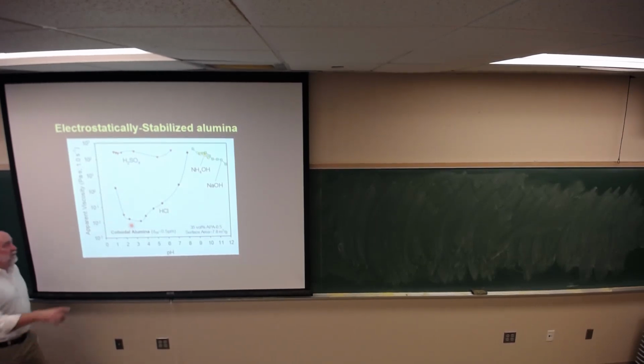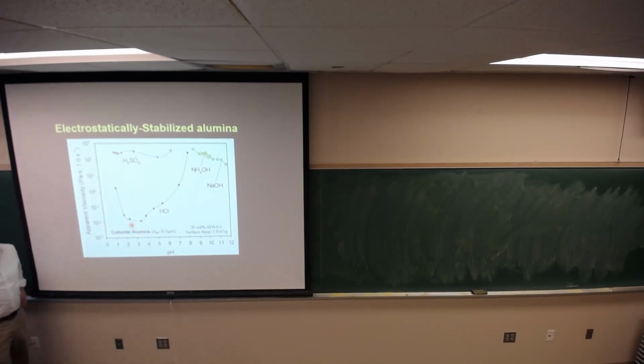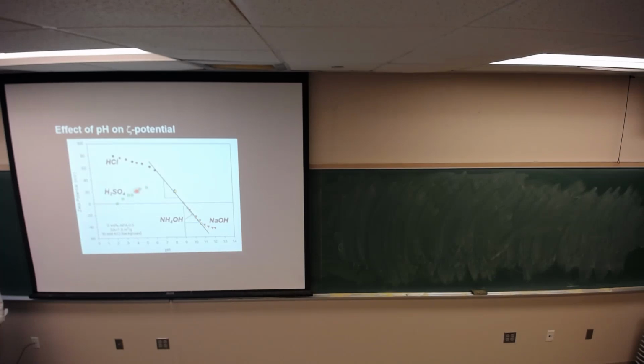And so what's happening is that this increase in viscosity here is due to compression of the double layer, also by an increase in the chloride ion concentration associated with changing that pH to that level. If I were to go to lower pH, I would expect that to go up further. Okay? Sulfuric acid doesn't make any difference where I'm at. I have always exceeded the critical coagulation concentration with sulfuric acid because I have a divalent sulfate ion in this situation. And my drop in zeta potential here is because of that divalent sulfate ion.